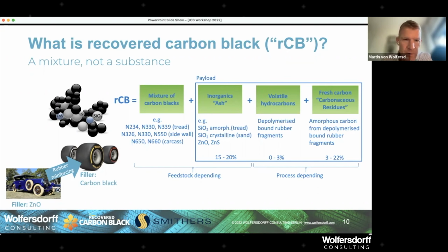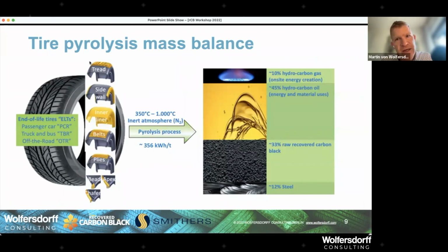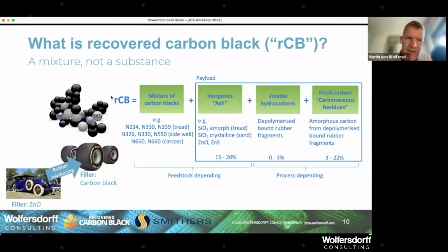Of course, when we go back and we look at the tire, the tread of an end-of-life tire is worn down. So we'll have a little bit more of the carcass composition than the tread. In the new tire, if we pyrolyze new tires, the composition would, of course, be something different. And the carbon blacks could come a little bit from the tread because it's worn down, as I said, from the sidewall, from the carcass, of course, from all the compounds. And then we have a payload, and that payload could be as high as 25% in European passenger car tire recovered carbon black, because in Europe, a lot of treads are filled with amorphous silica instead of carbon black.